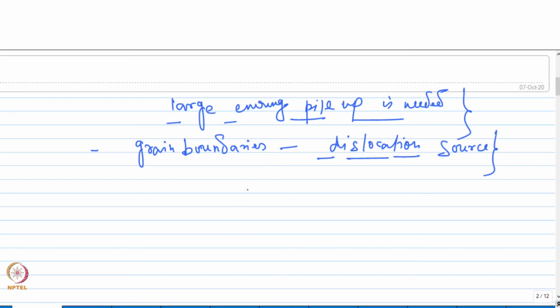And the other issue with this theory is the fact that for the pile-up to occur, the dislocation movement also has to be limited or restricted. And we have seen that the stacking fault energy will play a role in that. If the stacking fault energy is low, then you can expect the dislocation movement to be restricted. But for high stacking fault energy materials, the dislocation movement is much greater because of the cross slip. But in both kinds of materials, that means low stacking fault energy as well as high stacking fault energy, the Hall-Petch relation is valid. So this theory cannot really explain the effect of stacking fault energy. And as I said, on the other hand, you also have grain boundaries acting as dislocation source also.